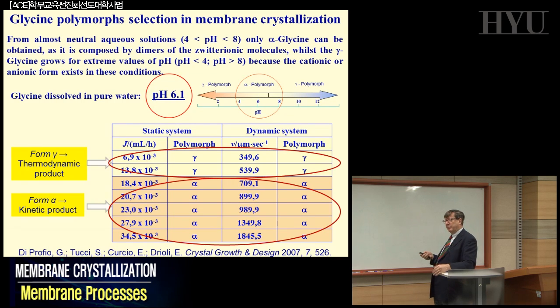So the same phenomenon we were observing with paracetamol, we started to work in a somewhat systematic way with some other compounds, typically forming different polymorphs. Glycine is a typical one that all of us have been interacting with, as an amino acid we have in our food, and you can have glycine in the polymorph gamma or in the polymorph alpha. At a certain pH, normally you have only the alpha form, and in other situations you can have a different kind of polymorph, the gamma.